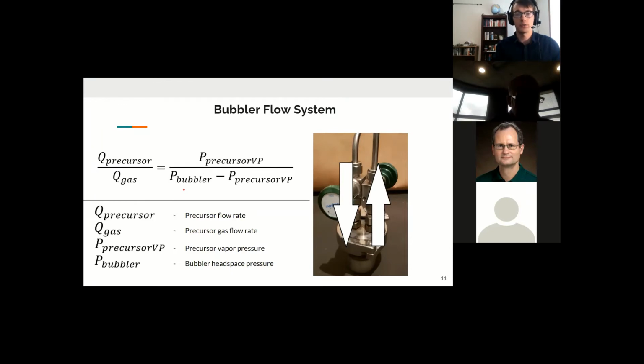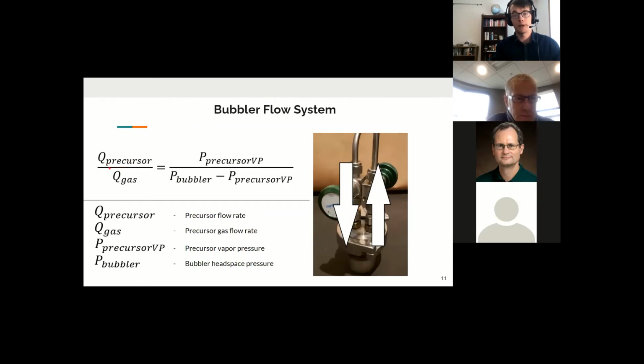So what you can get from this equation is that as you increase the bubbler pressure, the precursor flow will decrease. But because the vapor pressure of the precursor is so high, the bubbler pressure has to remain high to keep the precursor flow rates in a controllable zone. If the precursor gas is introduced into the reactor at too high of quantities, it will take energy from the plasma and the particles won't crystallize. They'll instead remain amorphous, which wasn't what we were looking for in our case.